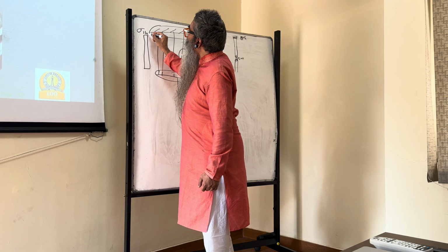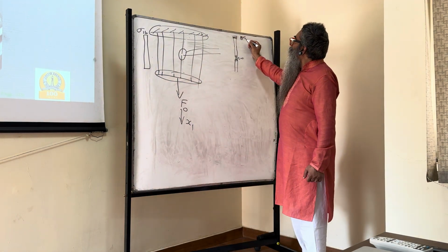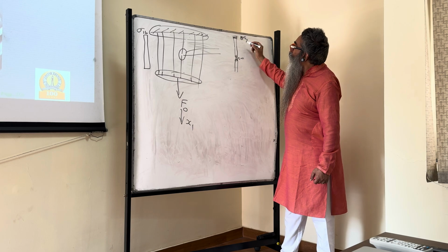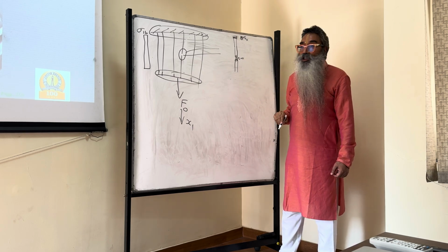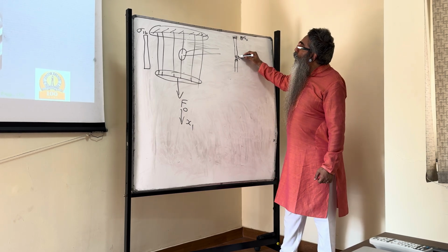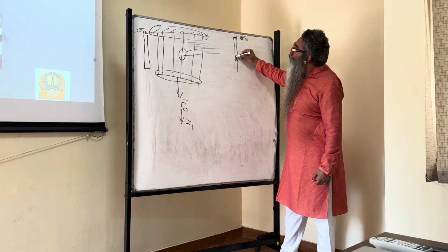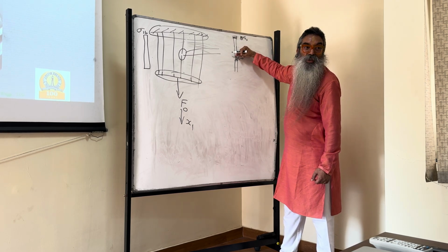Let's say sigma 1, 1 naught. That same sigma 1, 1 naught will be there. So in other words, it has to build up from 0 to that particular large value, and in fact it doesn't take all the distance to do that. It's just of the order of magnitude of this diameter, which is of the order of 10 microns, let us say.